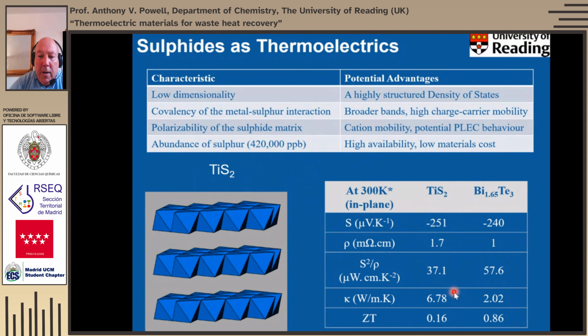What kills it is the thermal conductivity. So at 300 K, ZT drops from about 0.86 down by about a factor of almost 5, and that's predominantly because of the thermal conductivity.